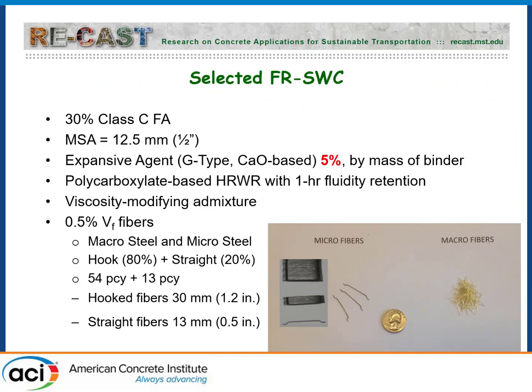So again, half-inch maximum size aggregate, 30% flat fly ash, expansive agent 5%, polycarboxylate VMA. Actually, that was interesting because initially we did think that we could manage to cast that concrete with a 20-inch slump flow. But you'll see later that we were not able to because there's a slope of 2 to 3% on the bridge, the crown. And then when we did some of the trials, it was not thixotropic enough. So we had to relax the slump a little bit. So it was highly flowable, but the VMA was still there to give it more robustness.